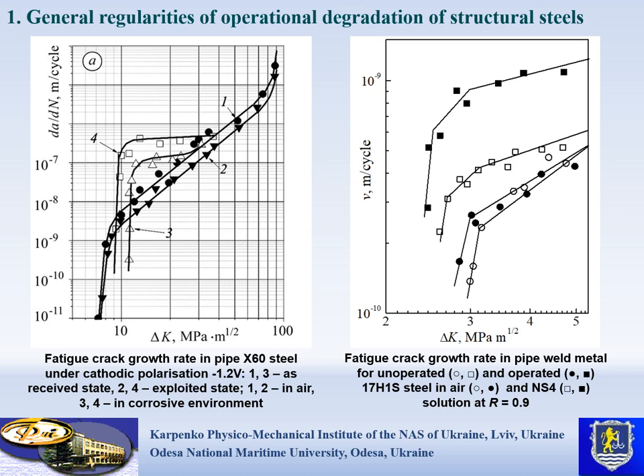Here we noted that fracture toughness is the most sensitive for evaluation of operational degradation. Concerning the parameters of fatigue crack growth resistance, we should separately consider the near-threshold region and the middle part of the fatigue crack growth rate curve. In the first case, we have to take into consideration the crack closure effect, since usually operation causes an increased crack closure effect.